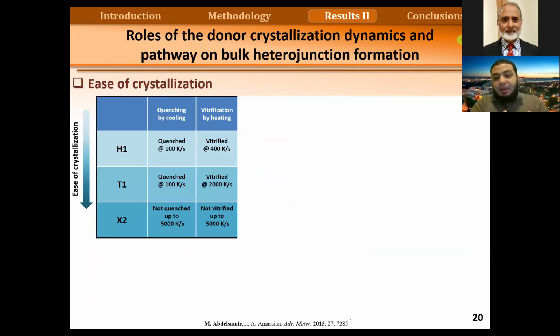So we applied this to T1, and then we applied similar studies to H1 and X2. But I will just go directly to the final conclusion. I will not go into detail on each one. What we have done is try to quench them from the melt, using flash DSC. We found that H1 can even be vitrified, and can be quenched more easily than T1. But X2, which is another derivative, cannot be vitrified up to 5,000 Kelvin per second. So the material X2 can be crystallized much more easily.